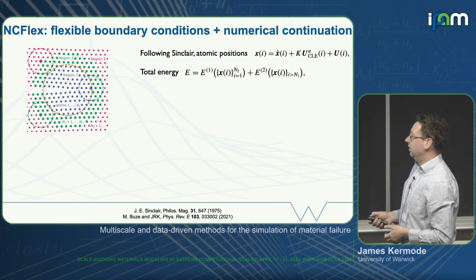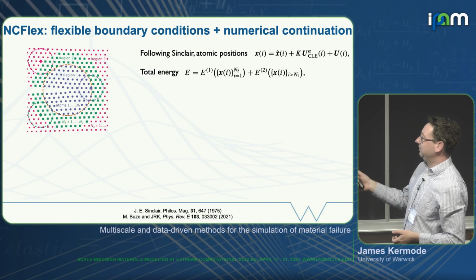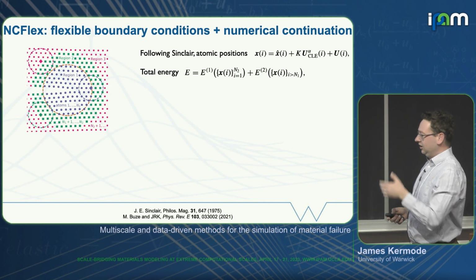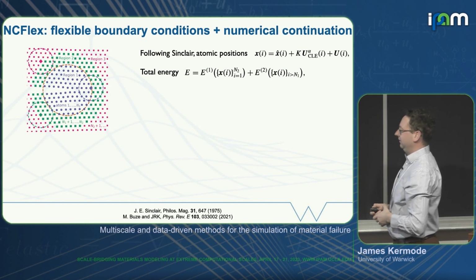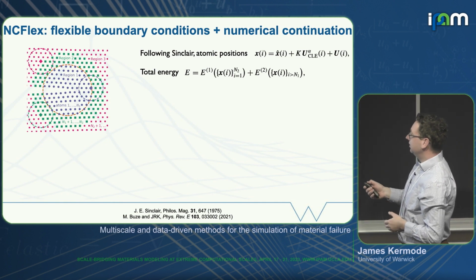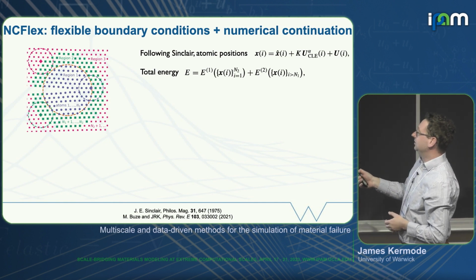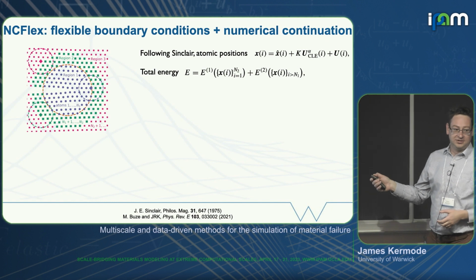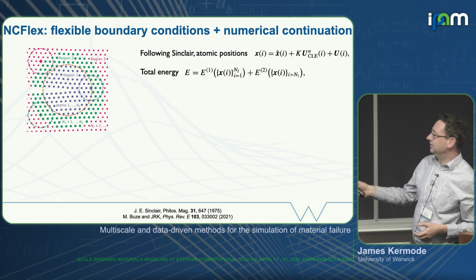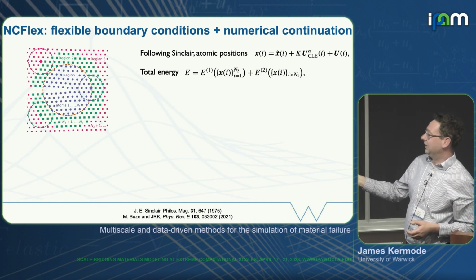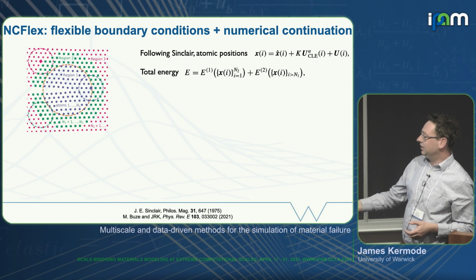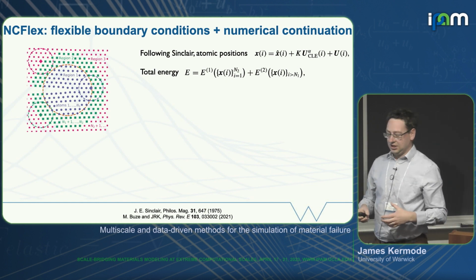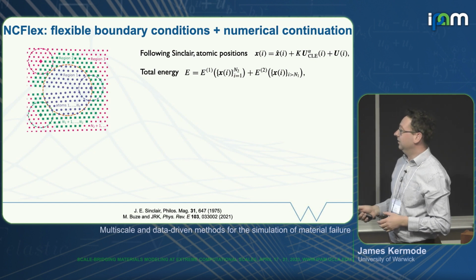And then the novelty of the work with NCFlex I'll talk about in a minute was to combine this with a numerical continuation approach. But first, a brief overview of the flexible boundary conditions. So the idea is we have crystal positions, we add a continuum linear elastic displacement field with a given stress intensity factor K, and then we allow atoms to relax just in this interior region 1 here. The outer regions are just there to couple with the continuum.